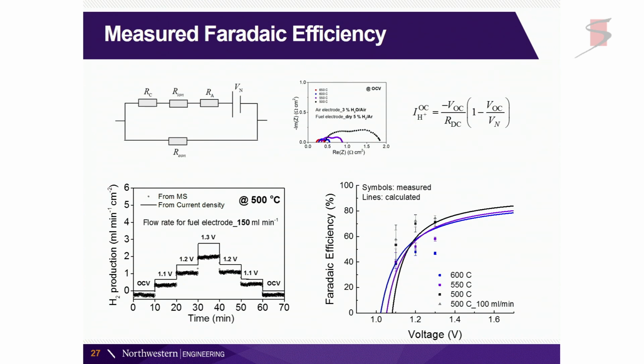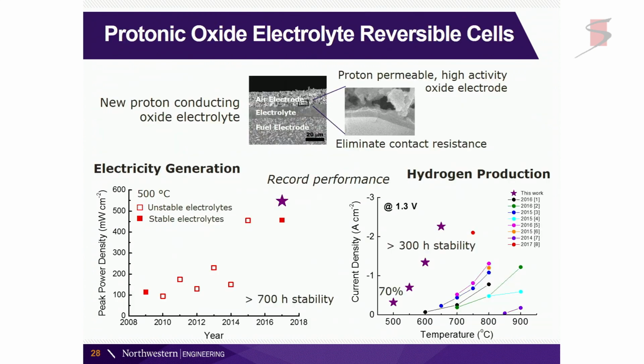And again, at open circuit, we see that there's a negative value. Again, this is calibrated through the impedance measurements. And then we can estimate the Faradaic efficiency. And now what's very nice, we can calculate what we expect based on an electrical model. And our measured Faradaic efficiencies here are actually quite reasonable, around 70% or so. And they increase when we go to lower temperature, as you expect, because you have less electronic leakage at lower temperatures. Okay, so now if we put this together, here's our electricity generation.